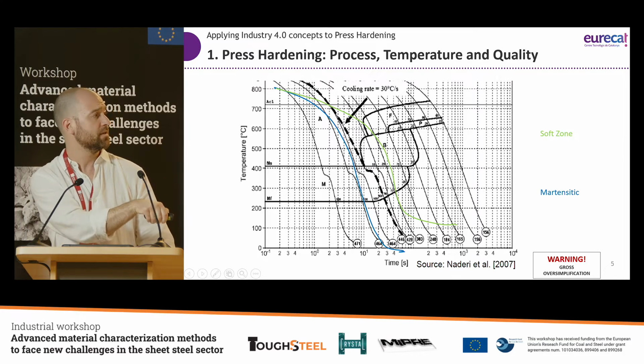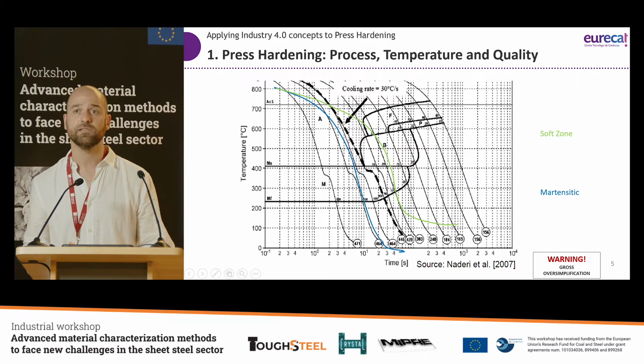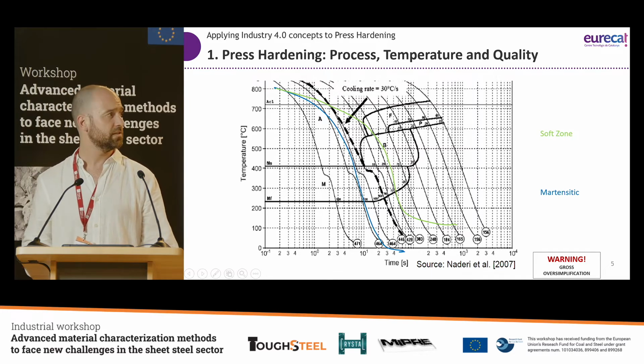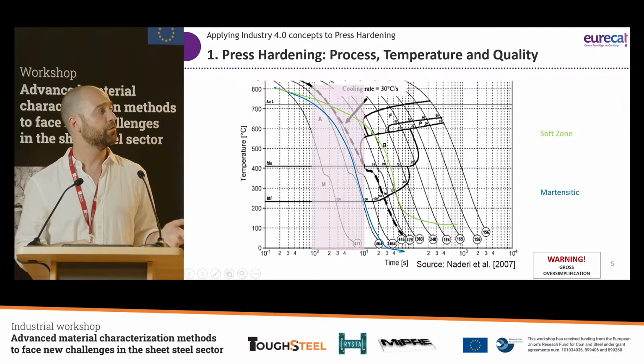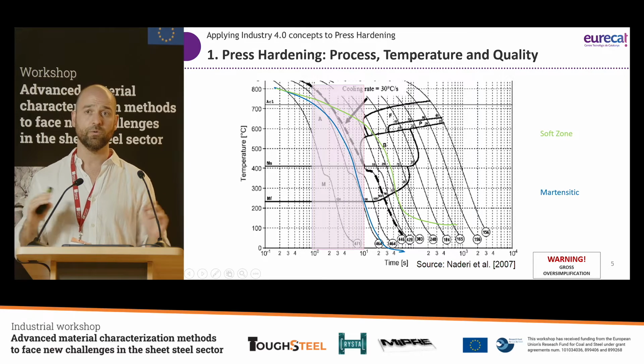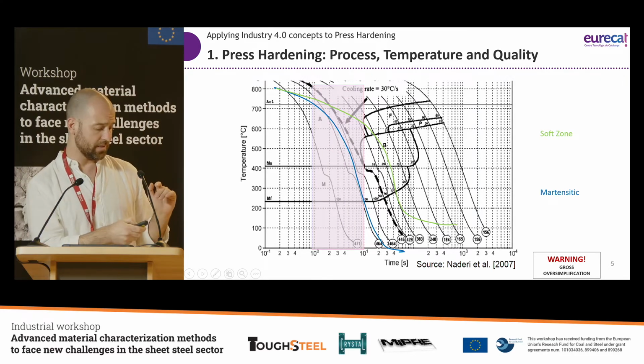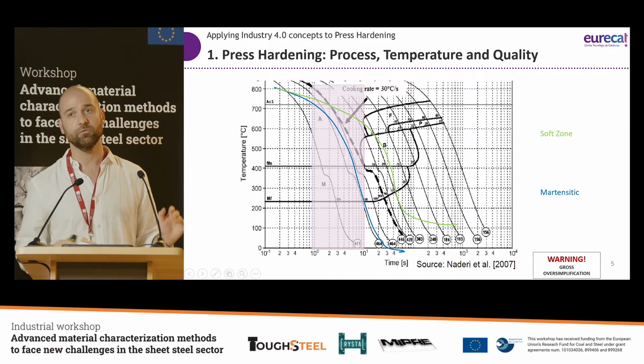Let's look at the times. I mean, you see, here we are crossing 600 degrees at 20 seconds, 30 seconds. This is not a natural process. This is something that we have to force. Actually, if we mind the process window and the time where we are cooling the die, it looks more or less like this. It can be a little bit longer, but we'll move in this range.